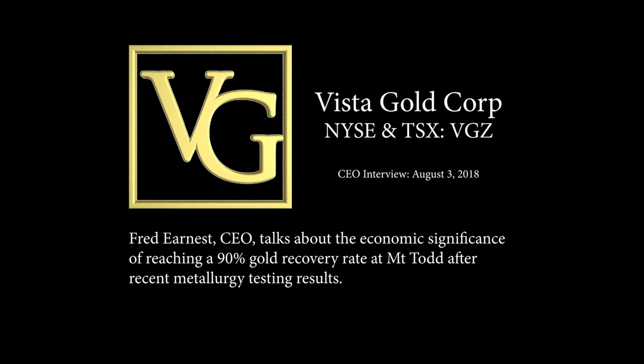And we did so in triplicate, so that this isn't just a one-off number, but rather that we were able to validate the numbers that were generated. And the bottom line is that due to two factors. One is that in this other type of grinding mill, in a stirred mill, and specifically in the IsaMill, the material grinds a lot easier than was projected. And so the first round of tests, the labs overground the material. They created a product that was much finer than what we expected, and even at that, they consumed less power to generate that sample. And so we've started looking at this from the point of view of, can we achieve a finer grind size with less energy consumption?